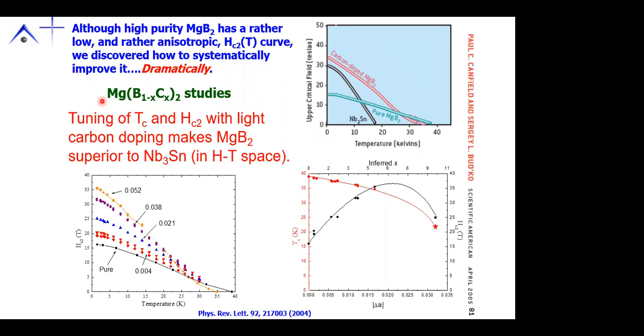And indeed, by titrating carbon onto the graphitic boron layer, we could see Hc2 increase as we went from 1%, 2%, 3%, 4%, 5% carbon substitution. We very weakly suppress Tc, but we dramatically increase Hc2. So we have carbon-doped MgB2 superseding the Hc2 of niobium-3 tin over the whole temperature range.